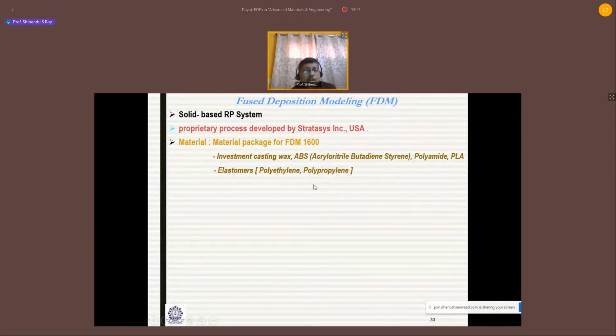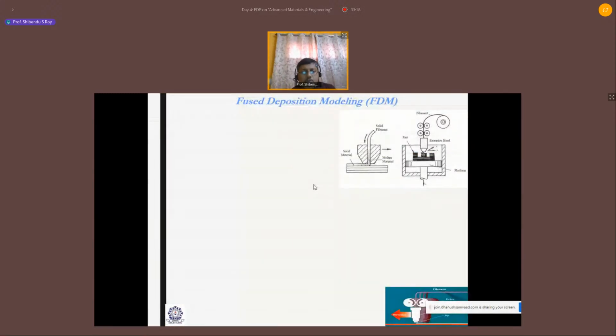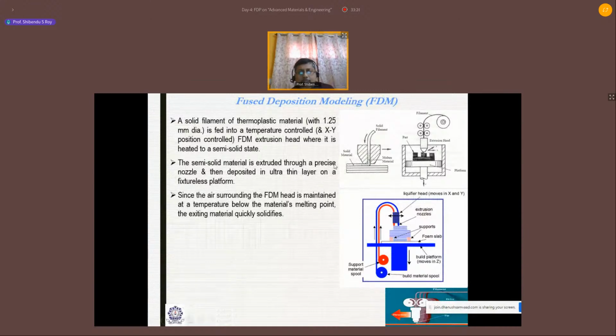The first machine was developed by Stratasys, and I would like to tell you the basic process here. This is the building nozzle, and the input material is in the form of a filament or wire. Our diameter is 1.25 millimeter, and that is fed into the temperature-controlled and XY position-controlled extrusion chamber. The process is very simple. Because of the feeding roller, the filament is continuously fed into this nozzle, and because of the temperature, it will become semi-solid, and because of the back pressure, it will come out from the nozzle of 0.4 millimeter diameter.